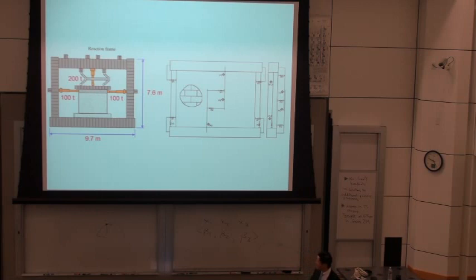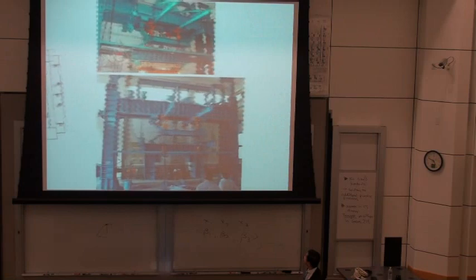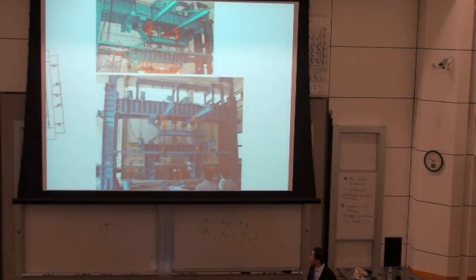But as I said, it's an older setup, because the problem is we have measured the displacements here and here, left and right. It is never really 100% parallel. And since it is not parallel, the moment middle point, the zero moment point, will move. So you cannot simulate a fixed boundary condition very well. Here are just some pictures of the lab.